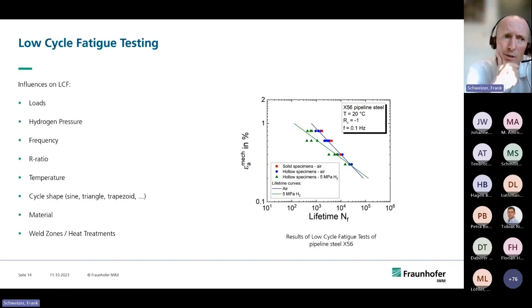They are quite good to do not only straining the material, but also cyclic testing. We especially look here at low cycle fatigue because we don't have very many cycles in the caverns or in the steels for the caverns. And the main advantage is really that you have a very closed system. With a normal autoclave system, there's always the problem that you get single molecules of oxygen inside of the system, and this alters the outcome of the experiments a lot.